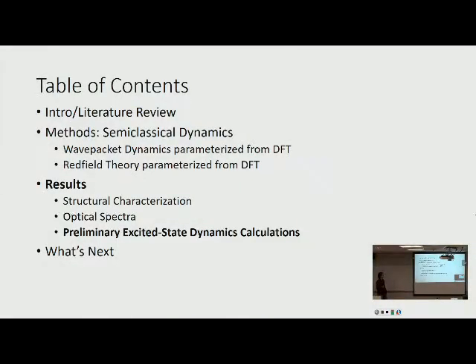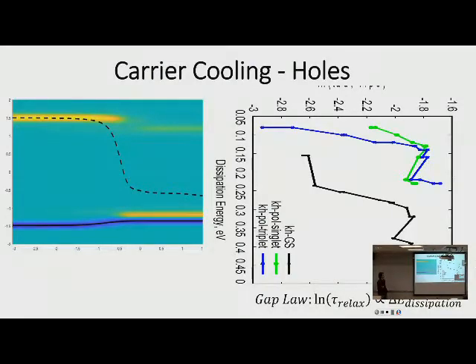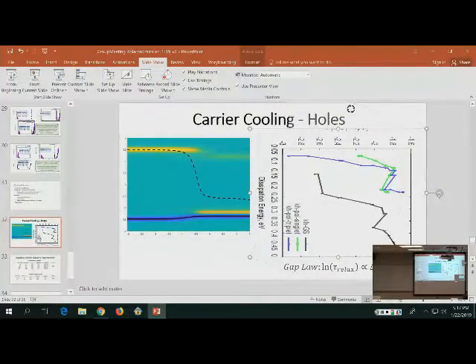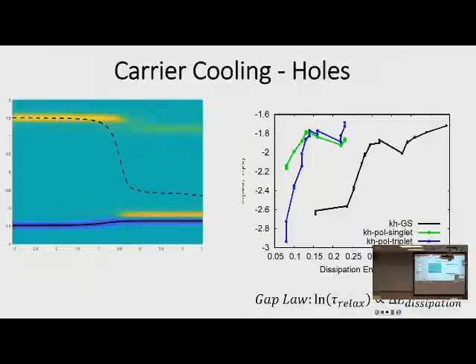So this is just some preliminary excited state dynamics calculations. I mentioned them earlier, but I'll say it again. We only have it for 2 models so far, the positive singlet Polaron and the positive triplet Polaron. The left shows our conventional green figures that we do to show carrier cooling in these systems. I'm going to have to work it out a little bit because, since we're changing the occupations, the code has to change a little bit.